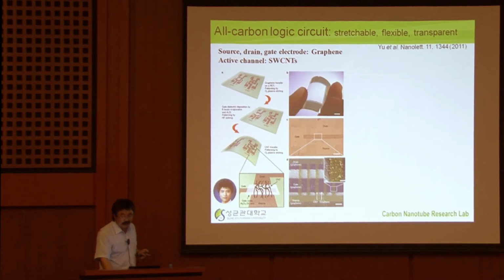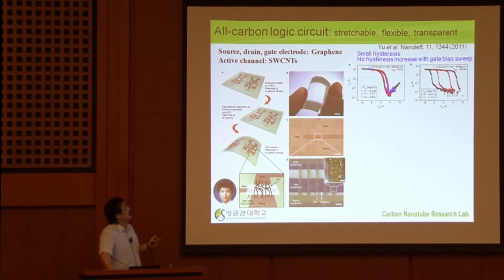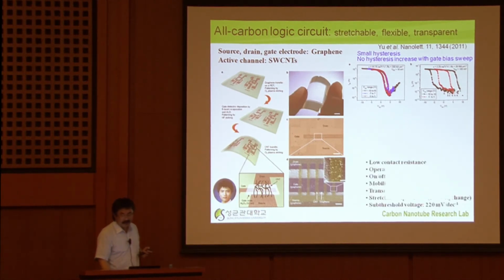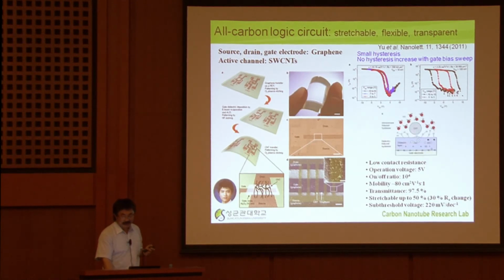With this one, if you look at it, now we try to increase this gate bias sweeping, and then no further hysteresis increased. This is one great advantage of using graphene as an electrode. I believe this is a very important procedure. And actually, with this approach, you can get many good properties of the transistor. So the future direction should be going like this, by combining graphene and also carbon nanotubes together.